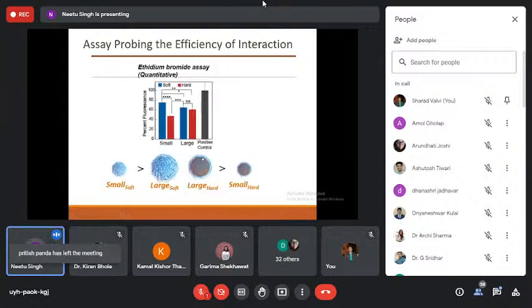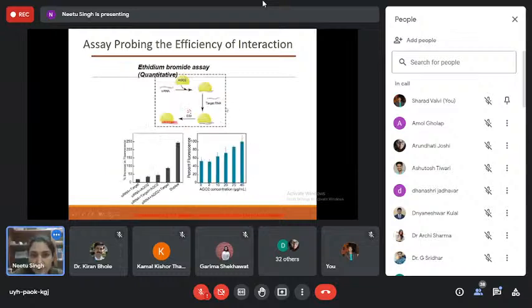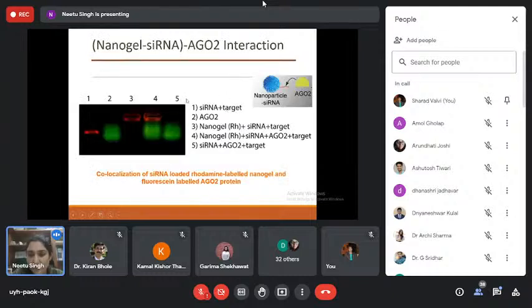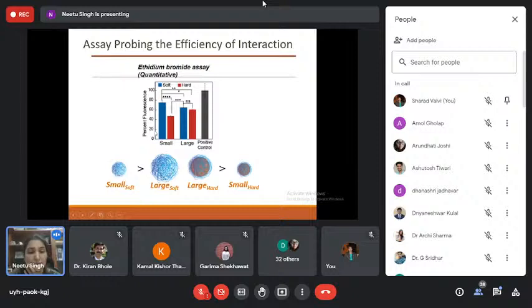Anyways, by doing these experiments, the two in-house assays that we developed, the ethidium bromide assay and the AGO2 interaction assay, we confirmed that a small soft particle is best for this interaction, followed by a large soft particle. Remember my argument where I said that either it has to be small, so that I understand, or soft also I understand. So if it is large, it has to be soft. What was surprising was this one, that a large hard particle is better than a small hard particle. And we were very surprised by this result. We were like, what is happening?